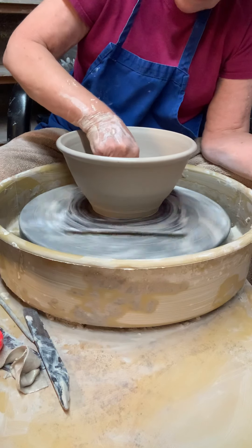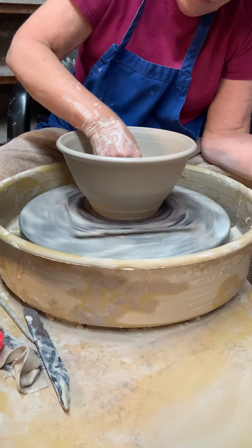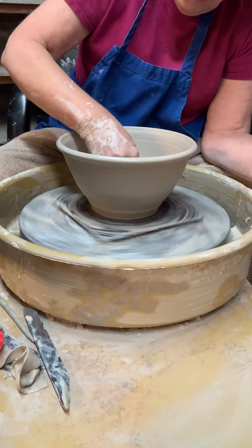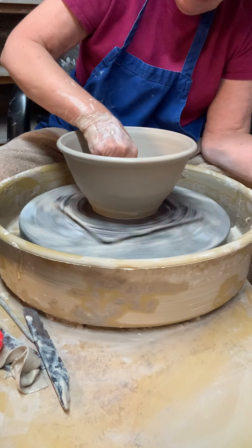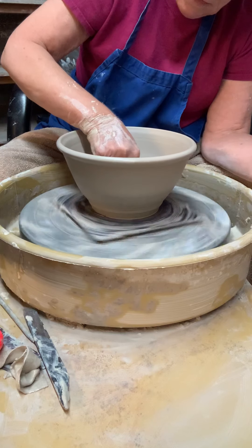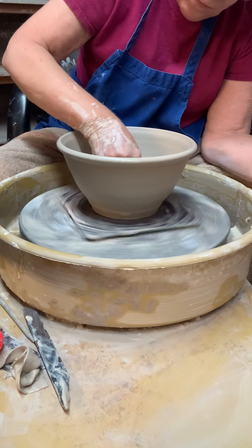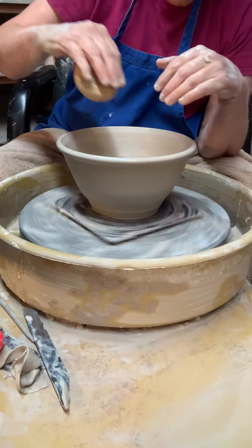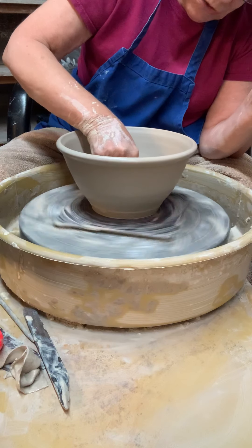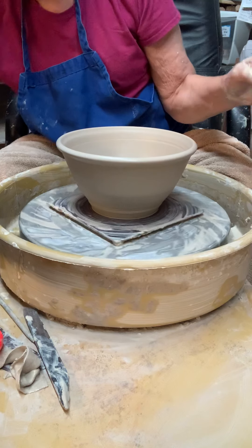When I make bowls, I like to also end up with my finger pressing from the outside in toward the center. That often helps — if you use pressure it helps prevent S-cracks. So if you're having S-cracks when you're making things, you're constantly pulling out, pulling out, but if you give some pressure and push toward the center at the end, that helps prevent S-cracks.